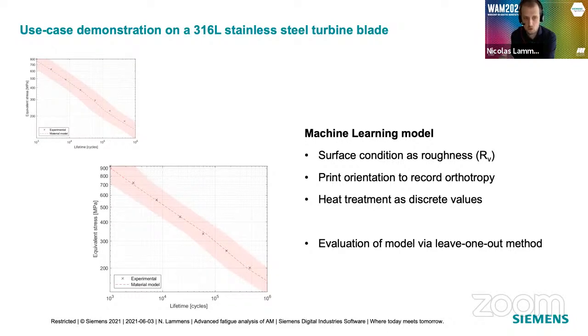You train your model with the remaining set, and then you predict that one SN curve that you removed from the training data, and you compare it to the actual measurements. And that's what you see for two different conditions here in the pictures. The red line is the mean prediction. The light red shaded area is the standard deviation. And the black marks are the test points. So you see that our model fits pretty well for both of these conditions.